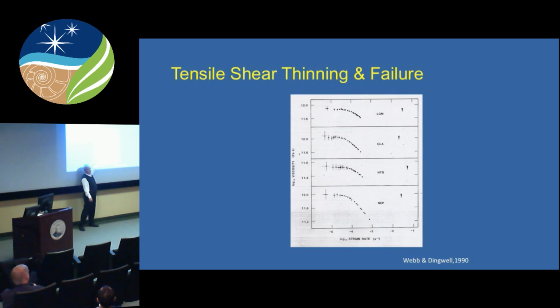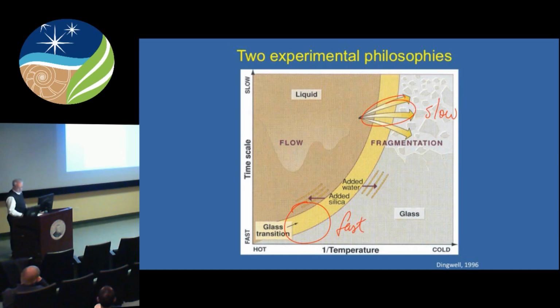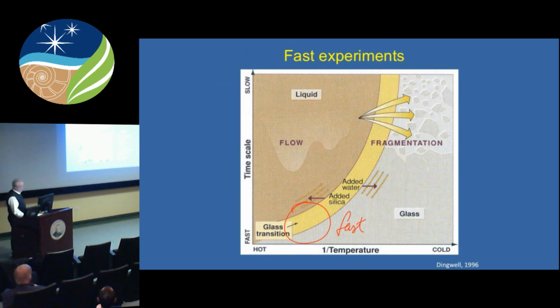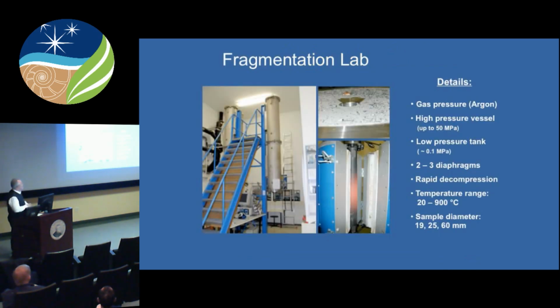And you may think, well, they're becoming solid. Why did they collapse in their viscosity? That's going the wrong way. The reason they're collapsing is that the structure is dying. The structure is actually being sheared out of its equilibrium state. So that, whereas here you could predict through spectroscopy the equilibrium structure, distribution, entropy of these liquids, here you no longer can. You're literally taking the atoms and moving them to the wrong place physically, and you're doing it fast enough that they can't snap back. So it's a collapse of the integrity of the material, which leads to defects in the mineralogist sense, and leads to disintegration of these materials.